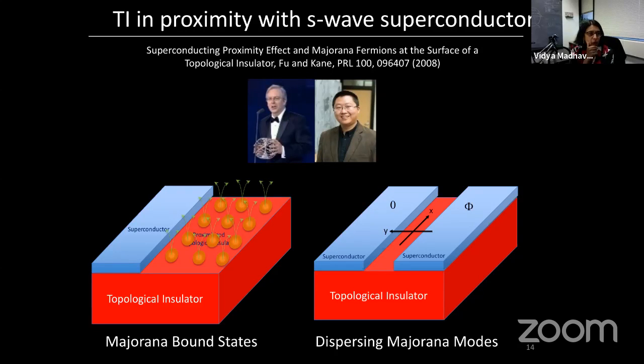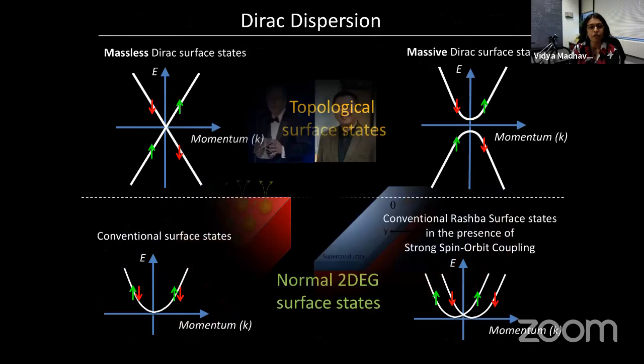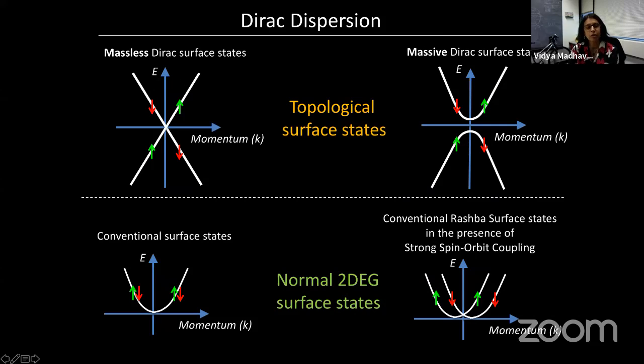Sure. But you have to satisfy all of these other conditions as well. So you need equal weights of particles and holes, but you also want to eliminate spin. Usually, at any given energy, you have a spin up electron and a spin down electron. You want to eliminate one of those electrons, and you have to take a lot of trouble to do that. Like in a topological insulator, you get it for free because you have only one spin species at a given energy. Just to compare that with a Rashba spin split system where you always have two spin species. You can see that here.